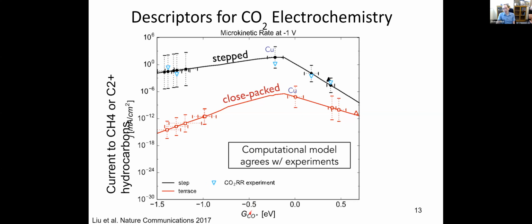Using this really, really simplified descriptor of the CO binding energy, we can rationalize why copper is special. So on the x-axis is the CO binding energy, the free energy of CO. On the y-axis is the partial current of methane or a C2 hydrocarbon. So we want this to be higher. And what we see is that on the right-hand side here, if your CO binding energy is too weak, you make CO, it leaves the surface, and you bubble off a bunch of CO. All of these points are the ones I just showed you, silver and gold and the others, that make a bunch of carbon monoxide. They bind CO too weakly to keep it around and do something cool. Everything on the left-hand side are things like palladium and platinum and other materials that bind CO so strongly that they sort of poison the surface, and then the only thing that's left is for them to evolve hydrogen.